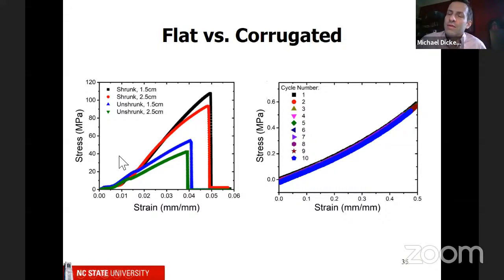First of all, you need to understand that this plot over here is referring to just the flat sheet. Imagine taking this piece of paper, grabbing it and pulling on it. When you do this, it goes to a very small strain, about 5%, and then it will break. The stresses required to do that are very high, hundreds of megapascals. When you do the corrugations with the exact same material, now you can go to about 10 times more strain, about 50% or even higher. And the stress is now orders of magnitude lower. It becomes effectively softer. It's like 0.6 megapascal, whereas over here, it's like 100.